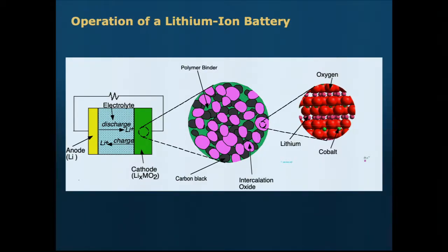The way you store lithium is by intercalation into an oxide. So typically there are these layered oxides. This is a picture of lithium cobalt oxide, where you have this layered structure. You have cobalt ions, lithium ions, cobalt ions, lithium ions, and you basically shuttle lithium ions back and forth in and out of the structure. So you store lithium kind of like in a material, like a sponge, right? In discharge, the lithium sits at the cathode. In charge, you pump it back up electrochemically to the anode, and then in discharge, you release it again.